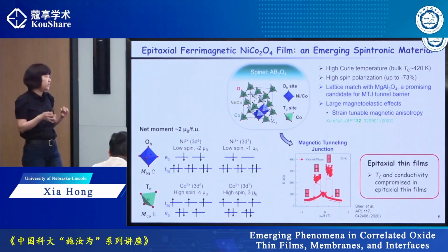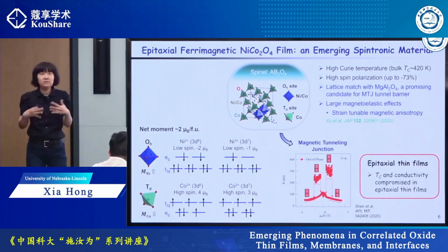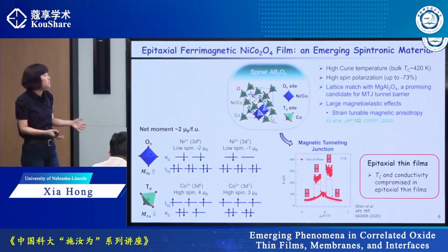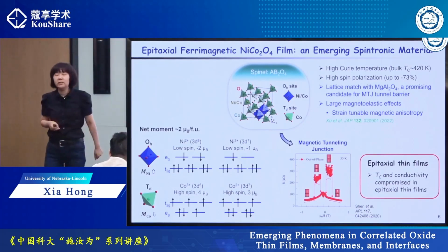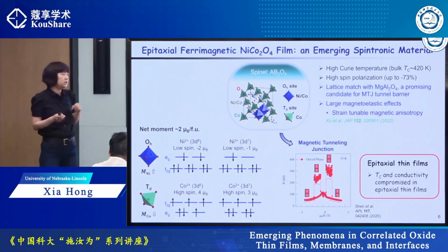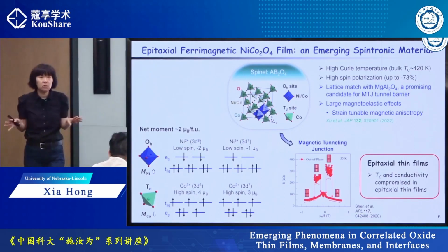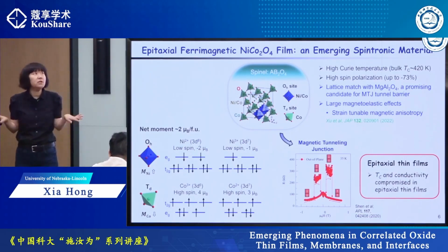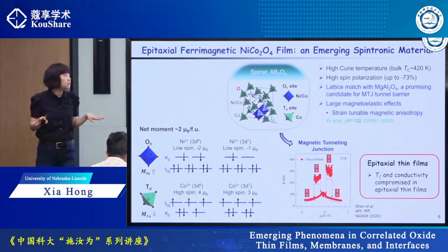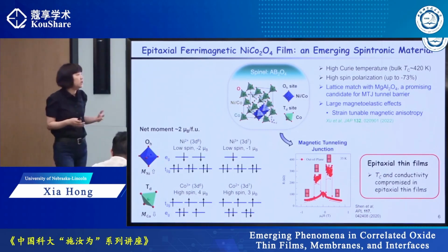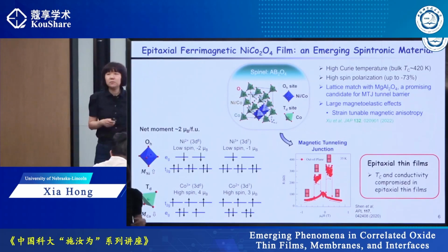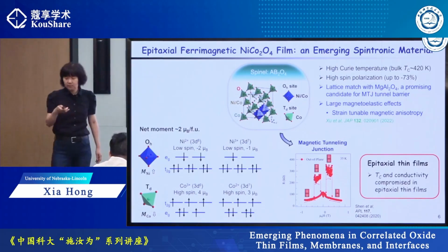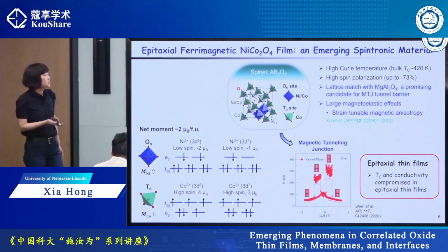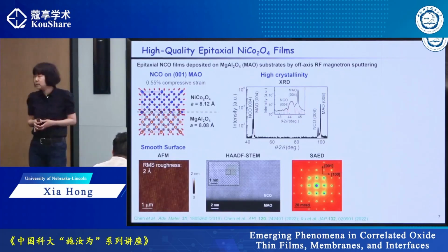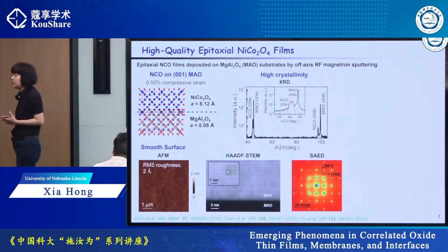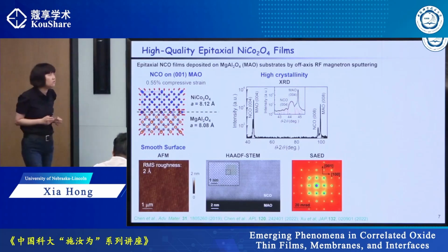So the idea is you need to grow thin films. Make a thin film, you can make it into magnetic tunnel junctions, but actually the thin film has only been grown for 10 years, and initial studies show the quality is poor. Curie temperature and conductivity actually are compromised in thin films. So we have recently been able to achieve very high quality thin films of nickel cobaltate.